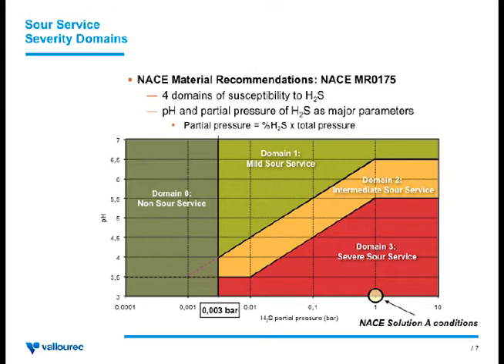The pH basically represents the acidity of the environment. The partial pressure would be the multiplication of the content by the pressure. That means that you can actually have the same severity on a tube if you use content that is pretty low but a HPHT well, or a high content of H2S in a well that would have a pretty standard pressure. So it's a way to be able to segment, project by project, what could be the risk